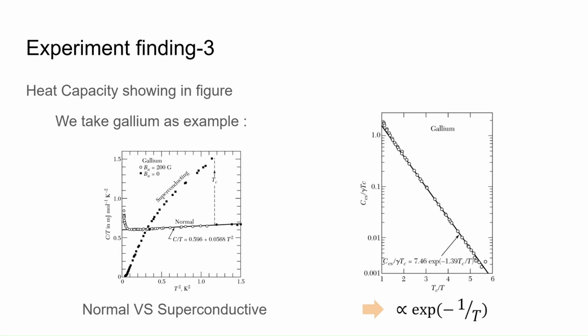Here is the figure we take as an example for the heat capacity experiment. We take gallium as an example. We compare the normal and the superconductive side of gallium. For the normal side, like the white dot, it lies on the line horizontally. But for the black dots, you can see it will slowly grow up to 1.5 on the y-axis. The y-axis here means C over T.